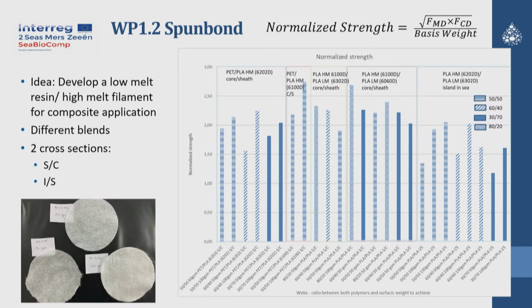Clearly, island in the sea offers, in spun bond, contrary to melt spinning, worse results compared to sheath-core for spun bond. We also tried different ratios. So a higher ratio, of course, seems to offer better properties, though not with all, because it depends on the weight of the non-woven.